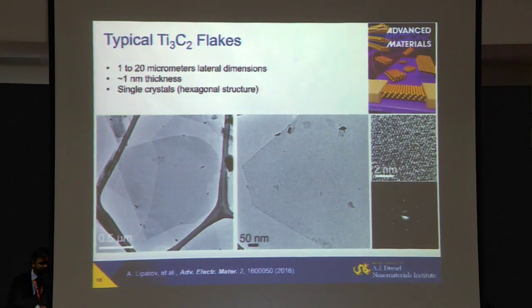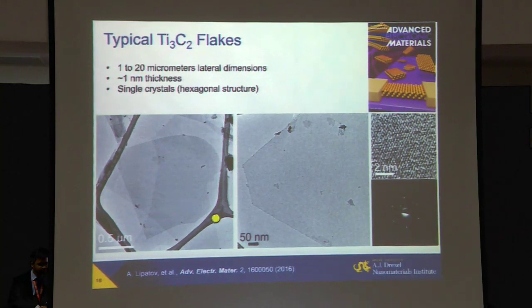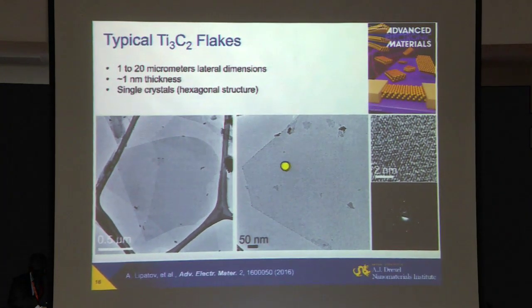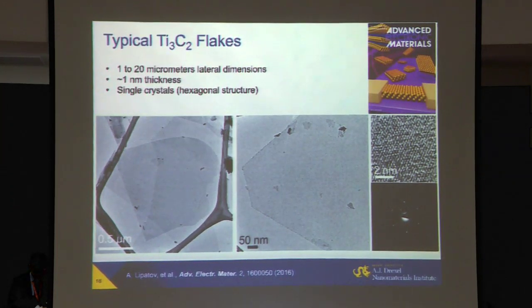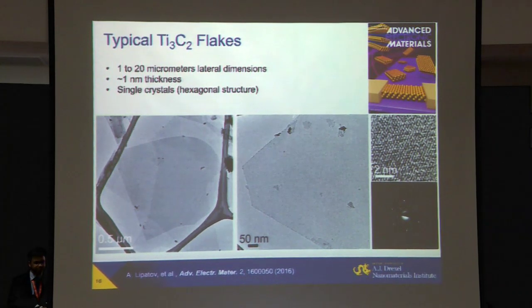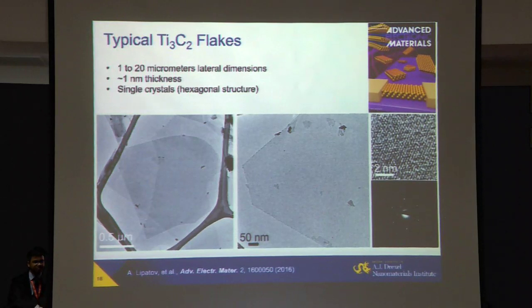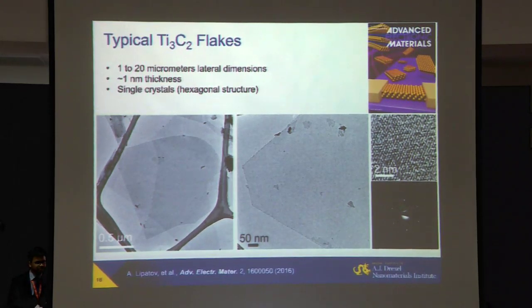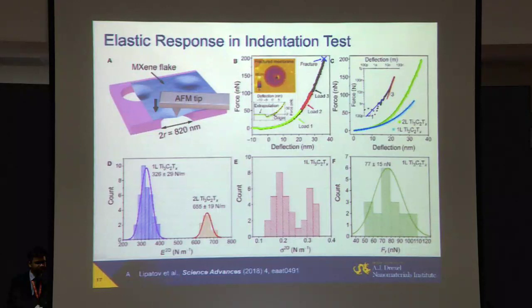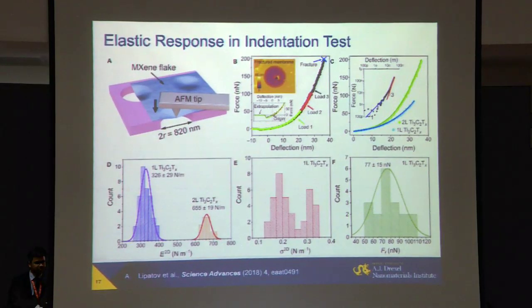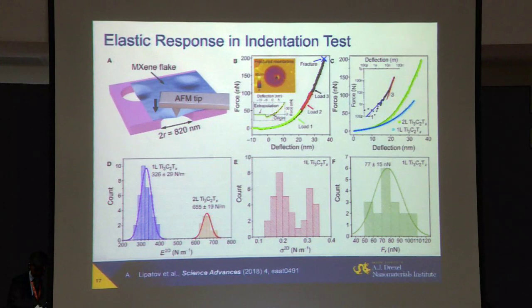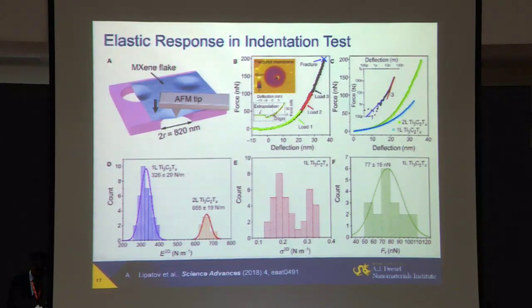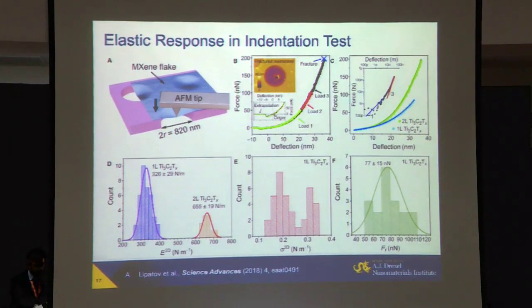But what is interesting, they may look very similar to what you see from some graphene or molybdenum disulfide. But you will not get a picture like that, for example, because graphene will right away drop. It's flimsy, it's thin. Bending rigidity of MXenes, because of just a few atoms thicker layer, is significantly larger, so it can actually stay suspended and keep the shape much better. And actually, it is pretty tough because carbides of transition metals are known and used, for example, as very resistant materials. Cutting tool, titanium carbide, tungsten carbide.